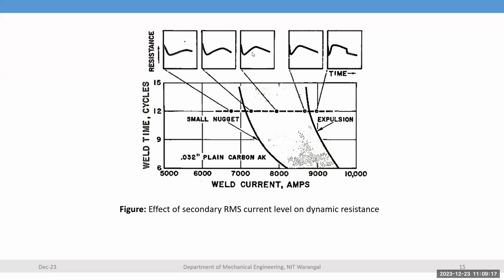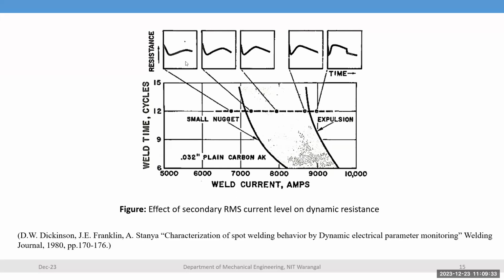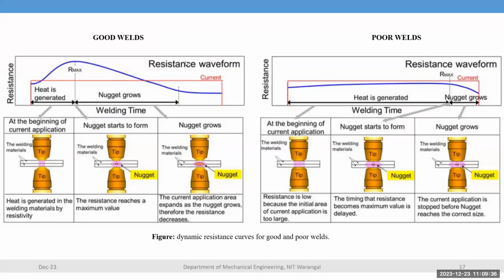So it looks like 1, 2, 3, and 4 look the same, but if you observe keenly at high magnification level, there is a difference in the profile of each and every parameter. Yeah, you can see the good weld and poor welds, how the resistance curve behaves. The welding time versus resistance, this resistance is maximum. Before this maximum heat is generated, you are supplying the current and the time, so the resistance is increasing up to this level. Then after that, it is going to decrease.